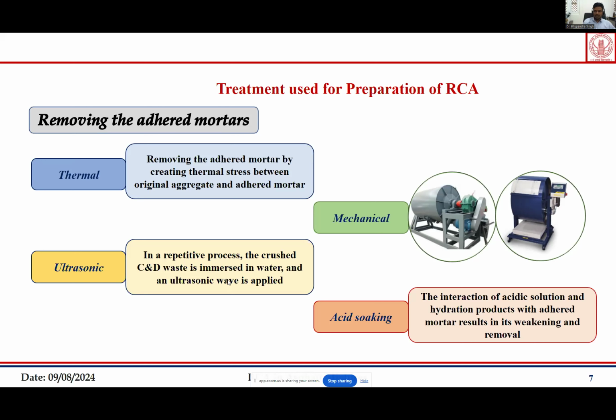Second one is the mechanical and most common one. In the mechanical method, we use some kind of mixer, or in the laboratory we use the LA abrasion machine also. So we use the abrasion and attrition techniques to remove that adhered mortar which is present on the aggregate surface. Then ultrasonic methods are also used.